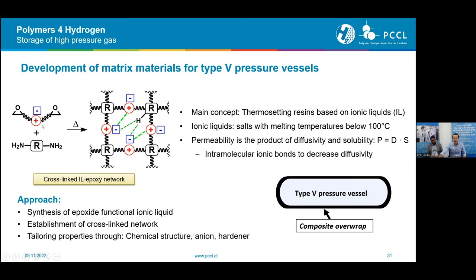So this is the ionic liquid functionalized with epoxy groups and then cured with an amine hardener, leading to this cross-linked network. So the approach here is to synthesize, of course, those epoxy functional ionic liquids and cross-link them. And then once again, we of course need to tailor the properties through the chemical structure, the anion and the hardener.